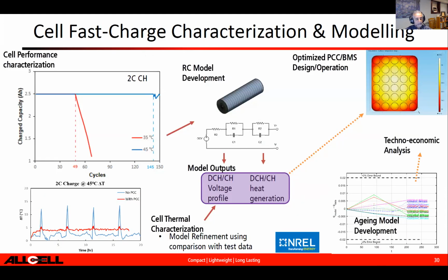This is just a summary of some of the work we've done with NREL. As you can see, if you have those high energy cells and you charge those batteries at a high C rate, for example 2C, the effect of temperature is very clear. If you go just from 35 to 45 C, you should be able to fast charge the battery continuously without degrading life. As you can see, the 35 C cell after 50 cycles fails, but with 2C at higher temperature, you're able to continue to fast charge the battery without any impact.